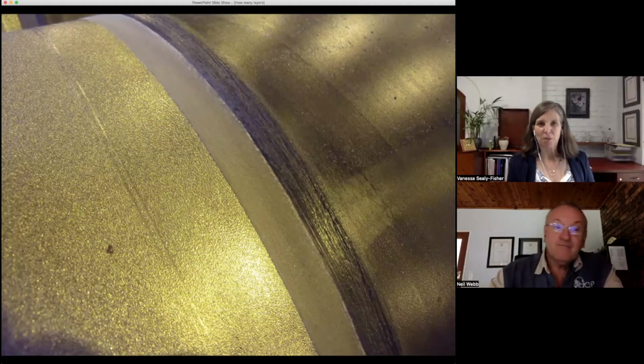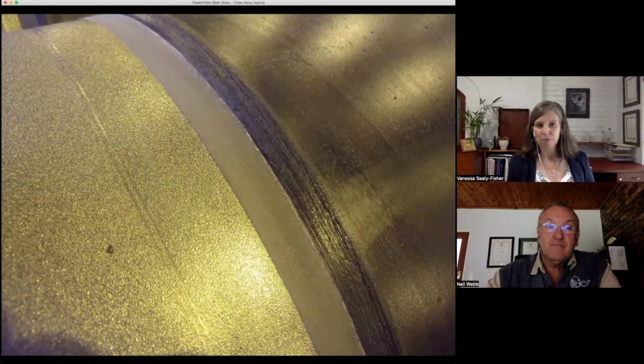In terms of getting your pipe ready for your FBE, you're going to have really critical surface preparation, cleaning, pre-treatment. Has that been improved over the years, or are we still using kind of the old original standards? I think that there's not really a lot wrong with the old standards, except perhaps that they were not stringent enough. So you have to have typically a SA3 surface preparation grade. You have to have a good mechanical profile. In other words, angular, not rounded. It has to be clean, and it has to be particularly free of dust. And that is possibly one of the most critical aspects.